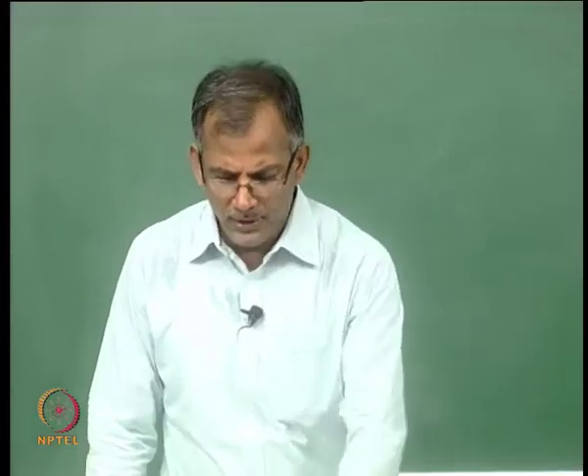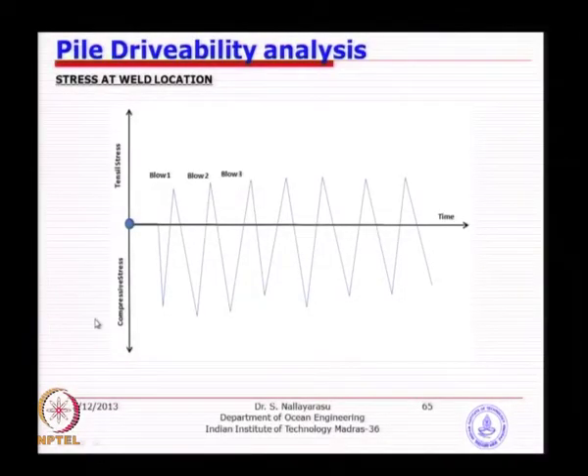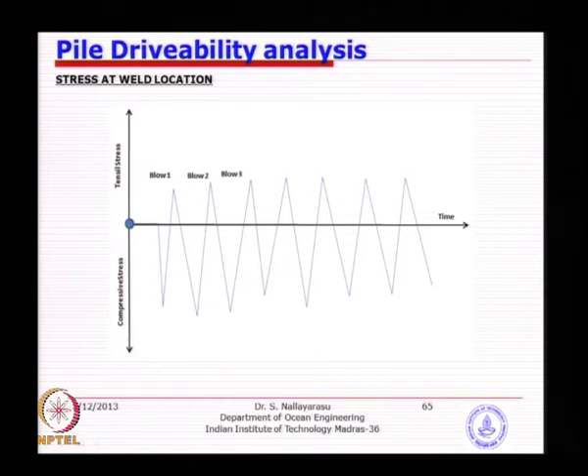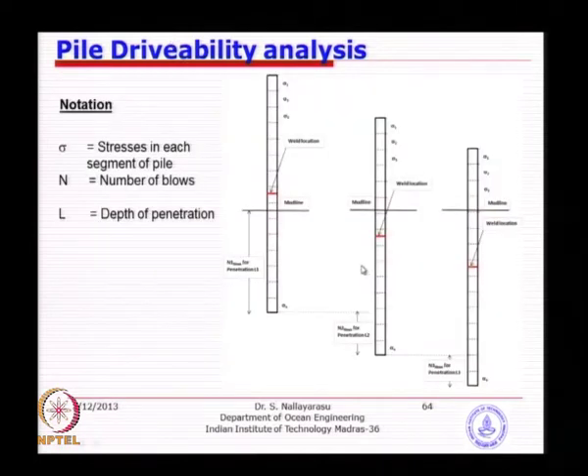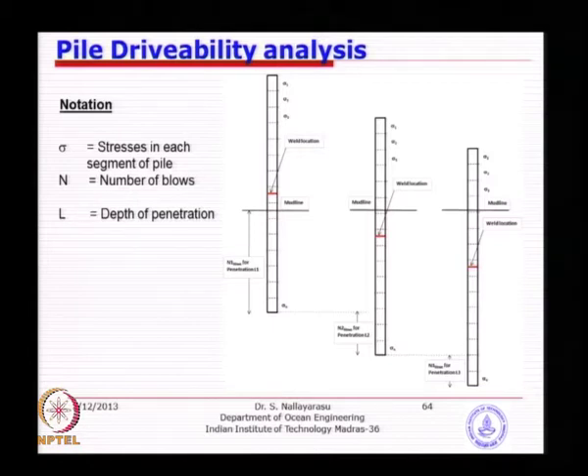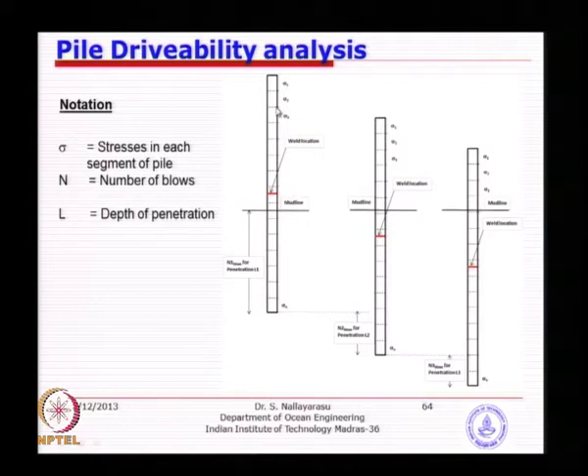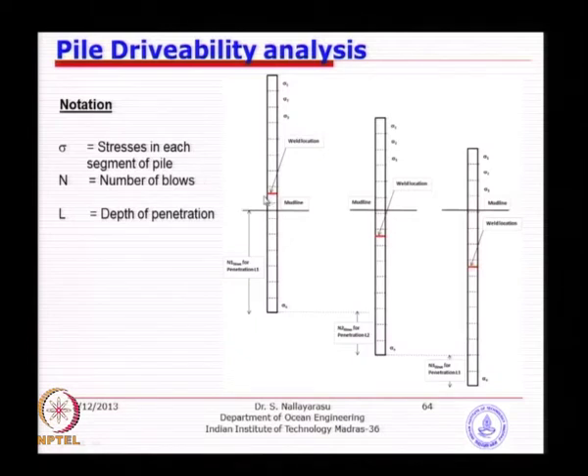The difference between the compressive and tensile stress gives you the range of stress causing fatigue, and the number of times you hammer is the number of cycles offering fatigue crack propagation along the weld. Evaluating the stresses at a particular location and the number of times that occurs is just a count of the number of times you blow the hammer. We divide into sub-segments to find stresses along the length, not to evaluate fatigue at every location.